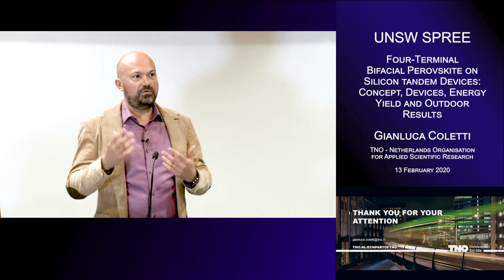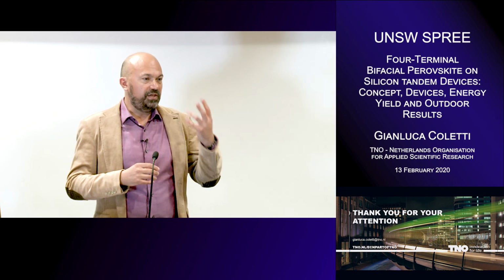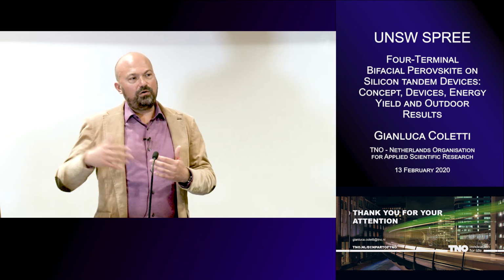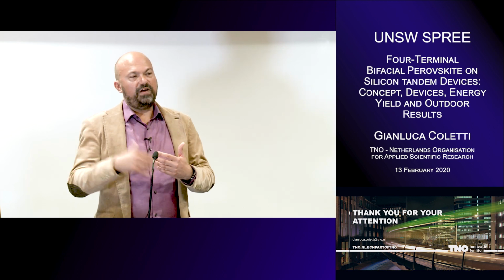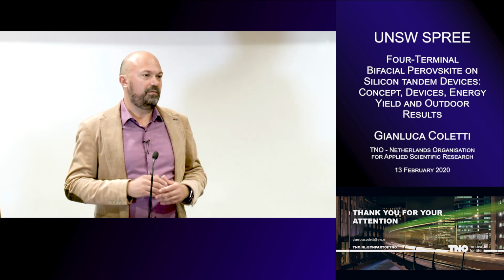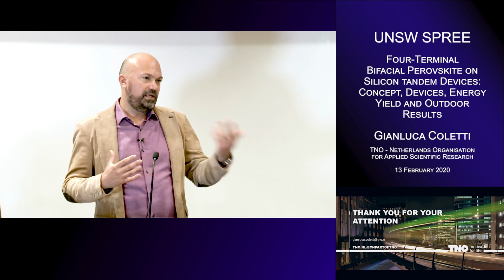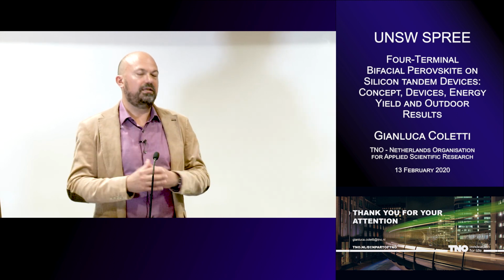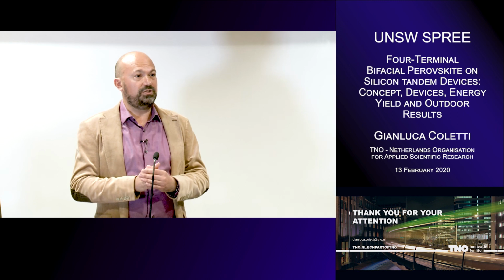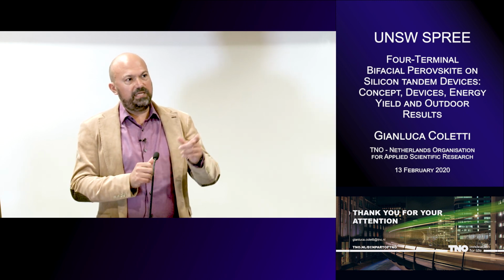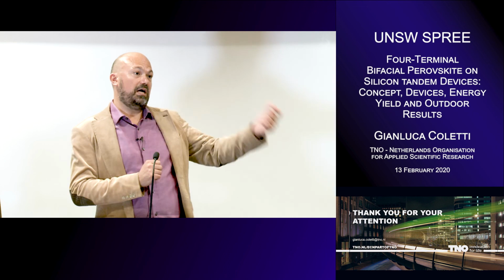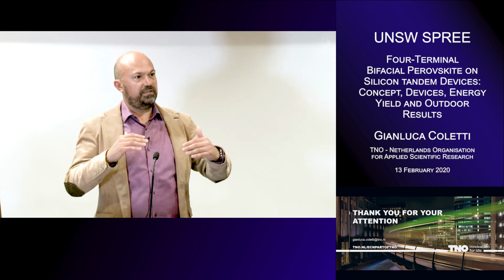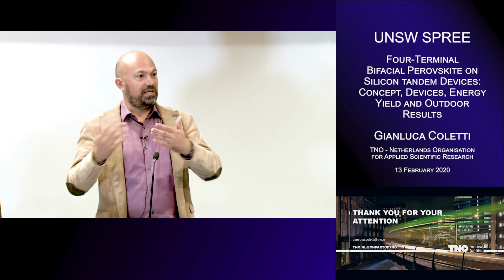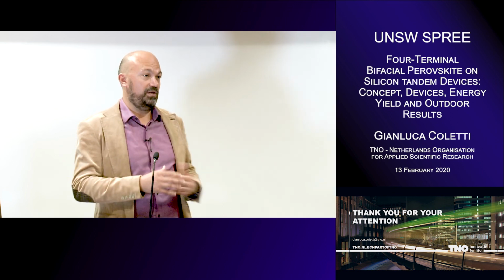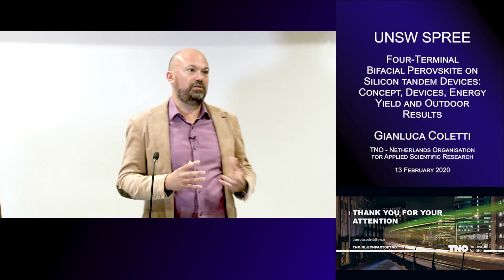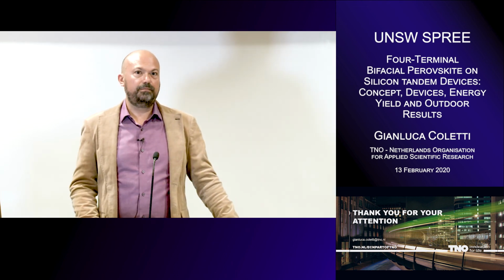And here, as a figure of merit, if you have an albedo of a certain amount, you have an energy yield gain of roughly half of that amount. So for 30% you have an increase of 15%, 17%. But it depends also from location to location. So in the paper we are writing now, we compare Amsterdam with Denver, which have different diffuse light, and the bifaciality is much better when you have diffuse light than when you have direct light. So there cannot be one rule for all.